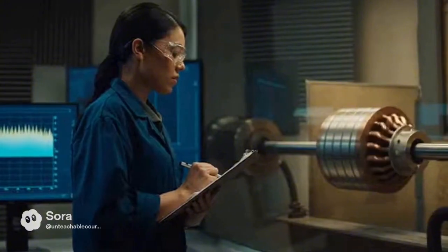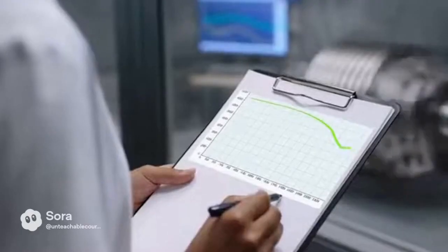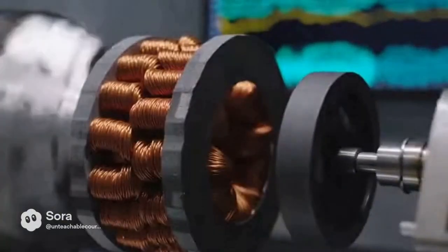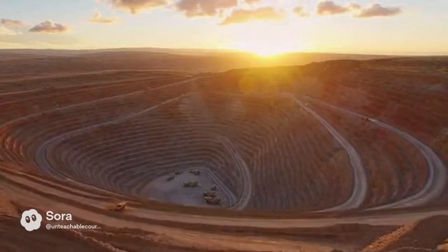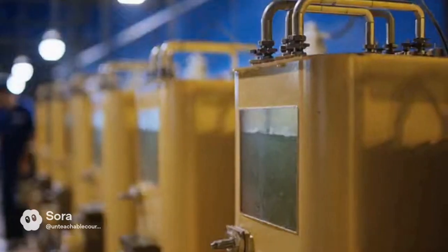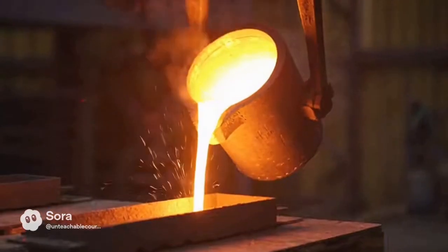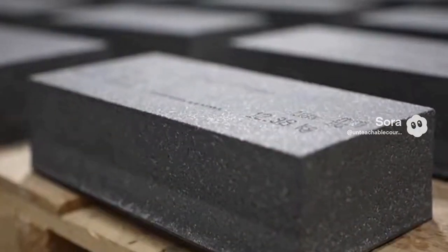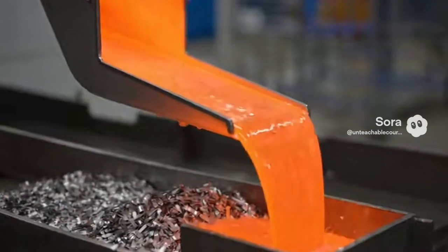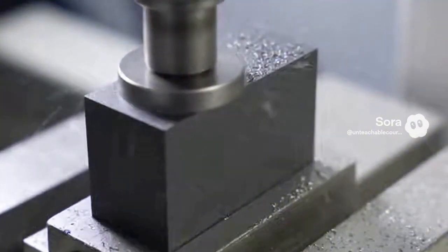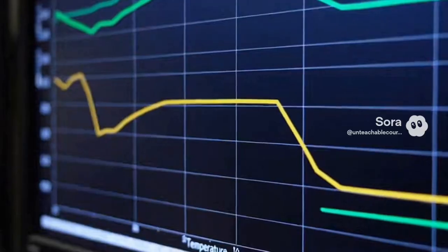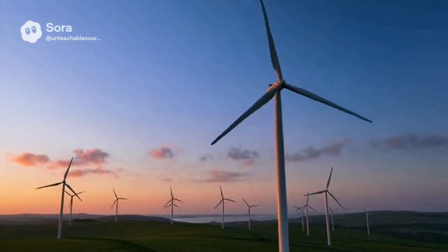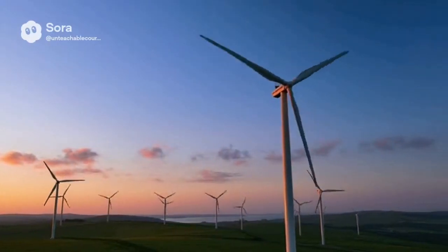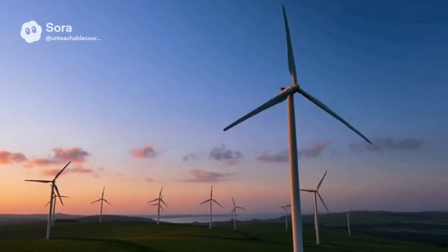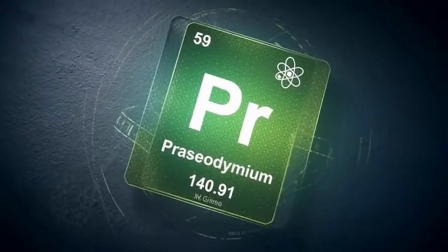The magnet is born, but not yet trustworthy. You machine to tolerance. You coat against corrosion. You diffuse a hint of heavy rare earth down the grain highways to armor coercivity where the magnet is weakest. All along, the recipe holds a quiet constant: neodymium and praseodymium together, in a ratio the plant can deliver every shift of every week. Put that magnet into a rotor and the earlier graph makes sense.